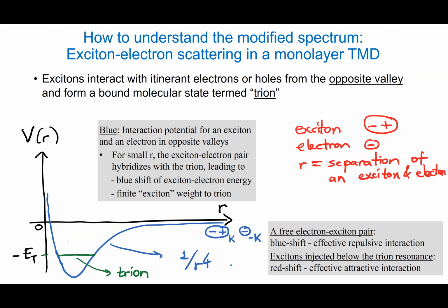Okay. So now if you consider a scattering state, a low energy exciton and electron approaching each other, the effect of this bound state is that the scattering state will hybridize with the bound state. As the electron and exciton distance gets smaller, they see the possibility to form a trion. It's off resonance, so they cannot occupy a trion state, but they will hybridize with it. And as a result of hybridization, the energy of the scattering state will go up. And so that is an effectively repulsive interaction. So the presence of this bound state means that the energy of the scattering state is going to be higher. And the closer this state is, the larger this energy shift is going to be, right?